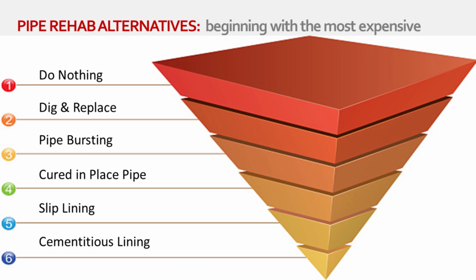Then alternative number 5 is slip lining. That's usually the next, and this is not rigid. These can be flipped around a little bit, but this is typically what I've seen after doing most of these processes myself. Slip lining can be a good fix in certain situations. It can fill voids when you're filling the annular space. Slip lining can handle a little bit of a bend, but not much, and they can't really handle a badly misaligned pipe joint. And it could cost a reduction of flow capacity, and you still have to do a little bit of digging sometimes with that type of process.